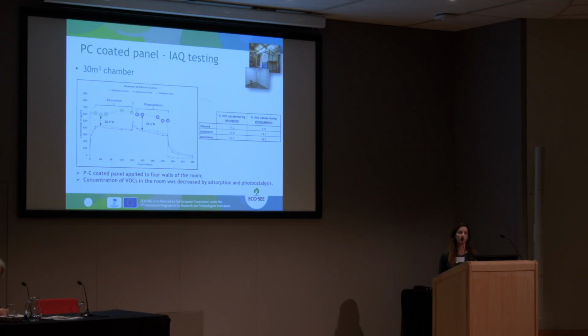So from this graph, you can't say if there was photocatalysis or not. So what I did, I measured the difference between the inlet concentration and the concentration in the center of the chamber during the adsorption phase, so the dark phase, and then in the photocatalysis. What we observed was that the uptake during the adsorption was less than during the photocatalysis. So this means that we had photocatalysis.